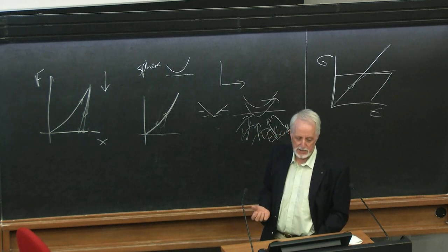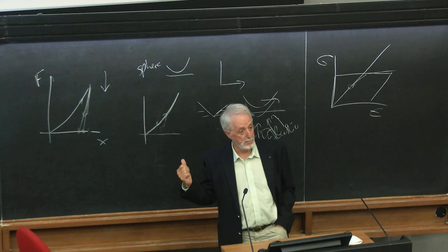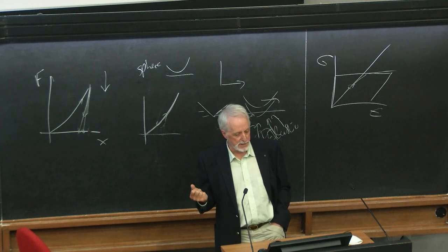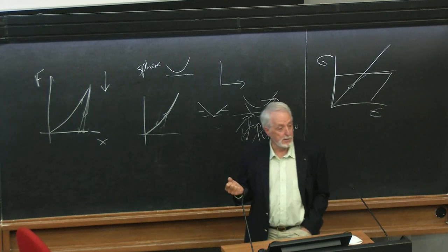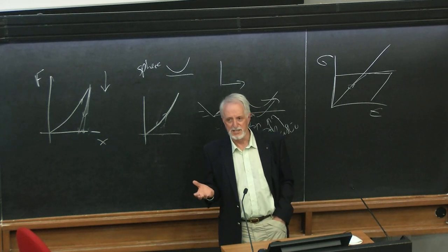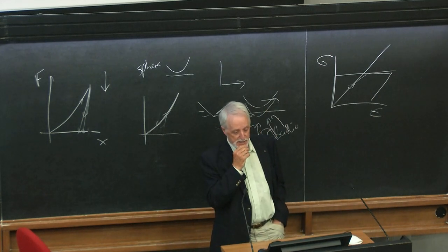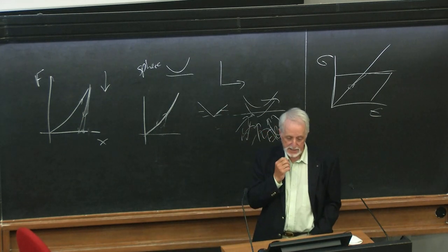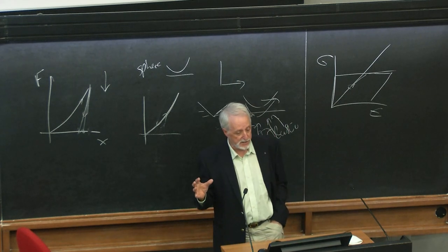For initial lateral loading, you get this simple plastic junction growth I described for essentially metallic materials. For materials which have a significant elastic recovery at the trailing edge, you get a more complicated picture, but essentially you can deal with it. And the important thing here at the end is that the transition from static sticking into kinetic sliding is affected directly by the interface friction. You can see that in terms of the energy dissipation.